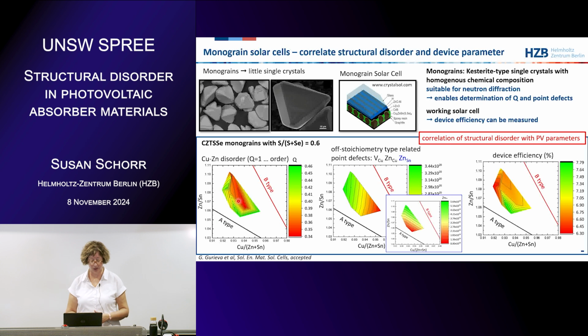So these are the cation ratio plots. And here is shown the order parameter. So green means less disorder. So we have less disorder here at that end and higher disorder when we go closer to the B type. These two figures are for the 3 point defects we have between the A and the B type. So copper vacancies, zinc on copper and zinc on tin. This is zinc on tin only. You see it's lower when you go closer to the A type line, of course.